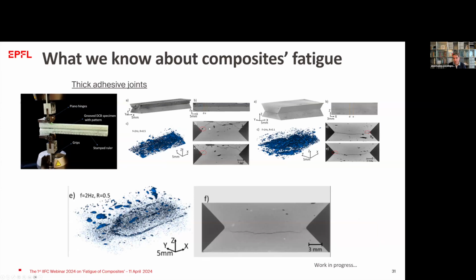And we've seen that the voids, so this is a micrograph, these are percentages of voids in the materials, different percentages of voids. So a lot of voids, less voids, or few voids. Although it seems a lot, it's less than 0.5% of voids in the bulk of the material. And we see that the presence of voids can significantly change the crack path in the material. In this case, where we have a lot of voids, the crack path is changing a lot, shifting from the mid-plane. In other cases, the crack can initiate from voids, or the crack can more or less be in the mid-plane when the voids are fewer.